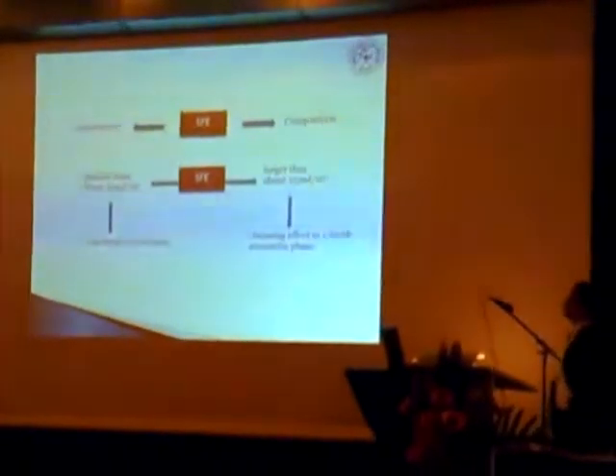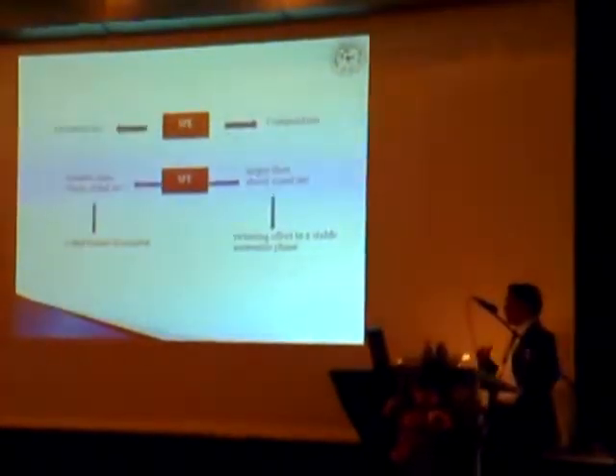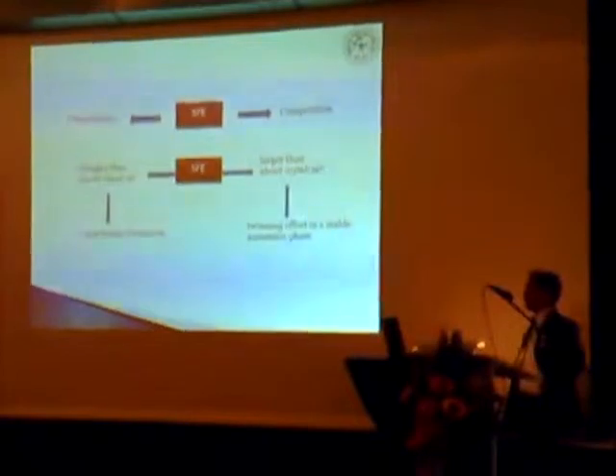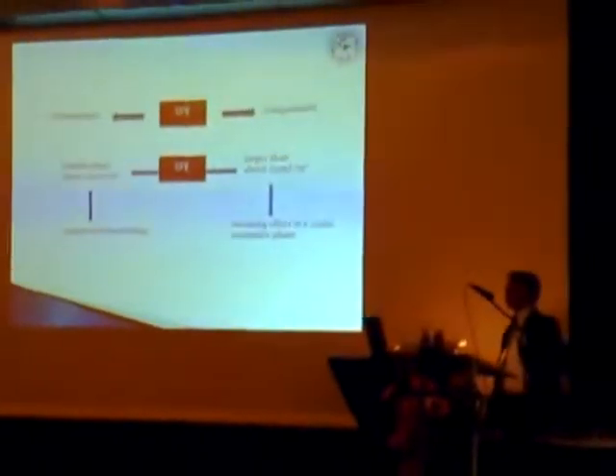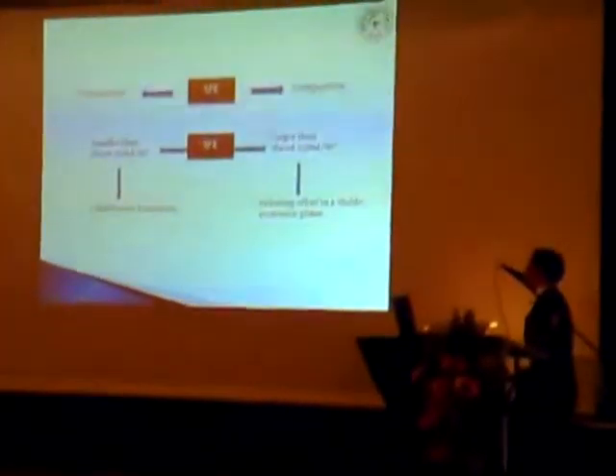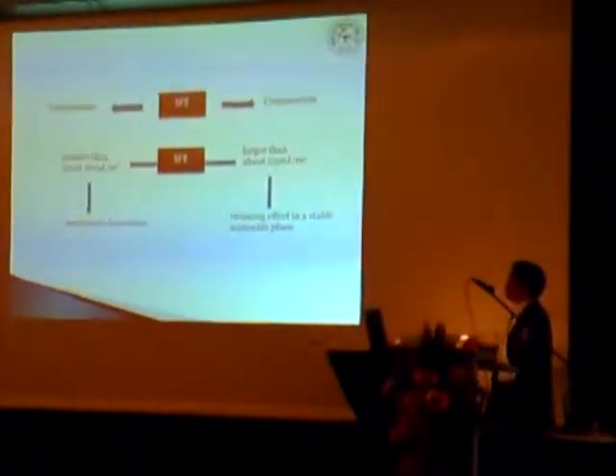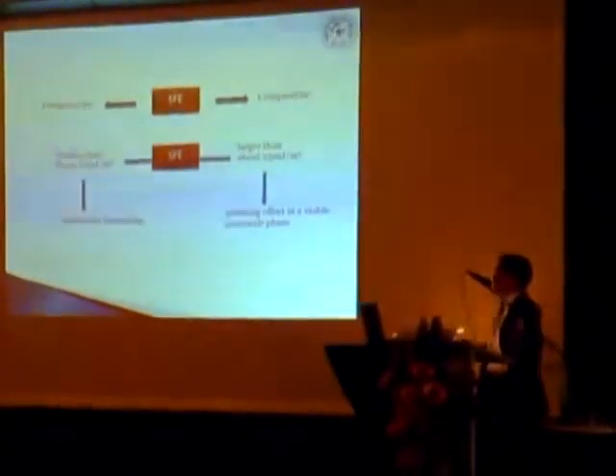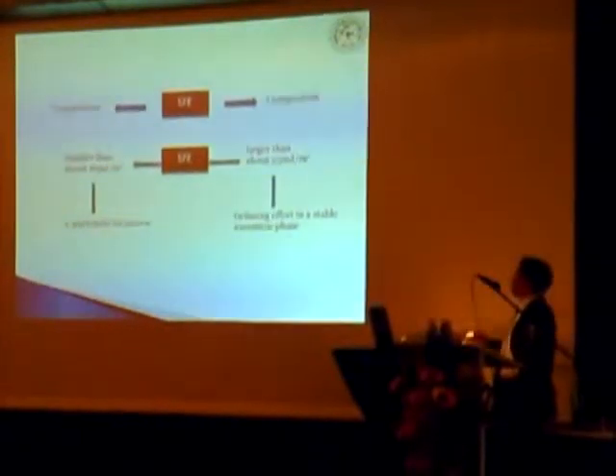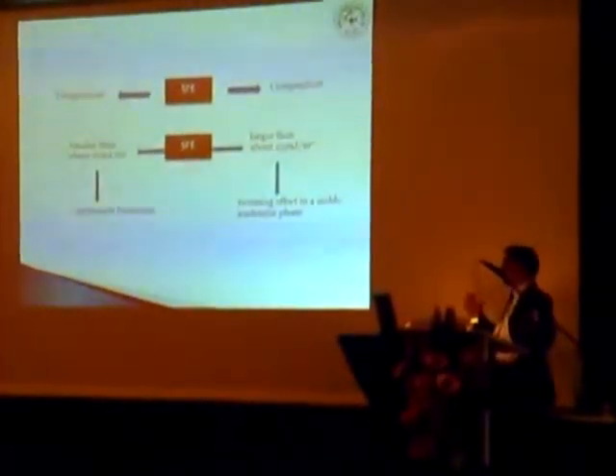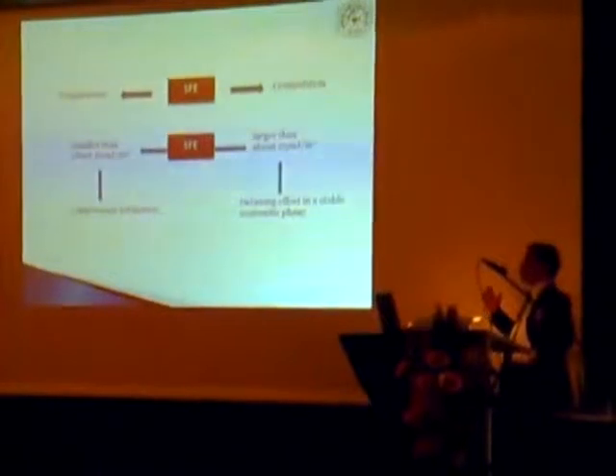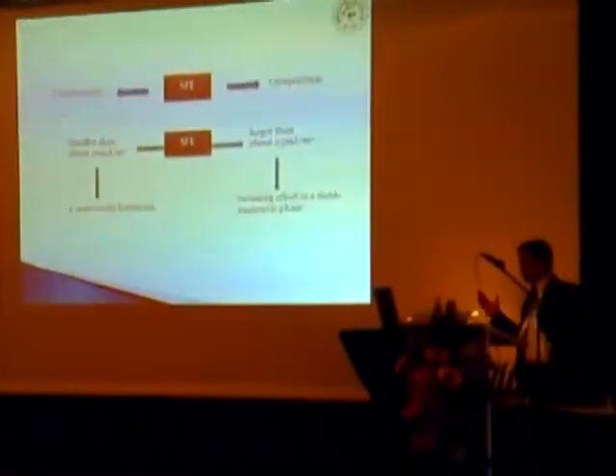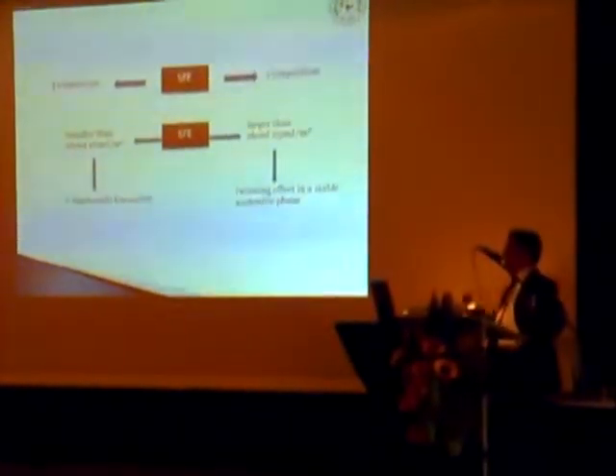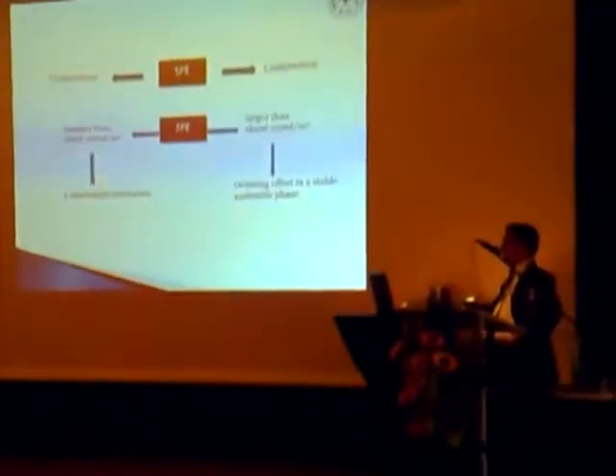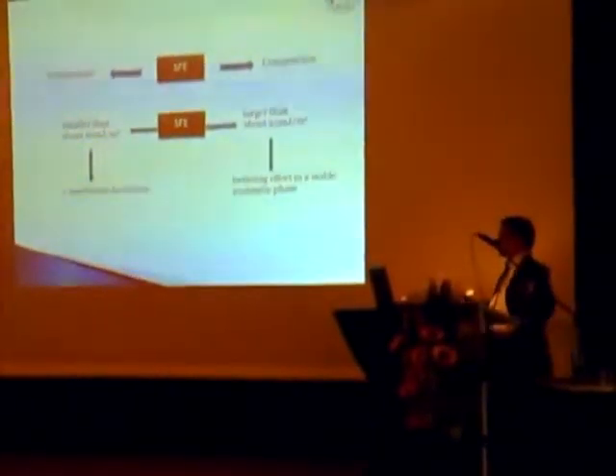And stacking fault energy is proportional to temperature and composition. There is a lot of work on this in twinning-induced plasticity steel because it is thought of as an automotive steel, and that's why people are so involved in that. They say that if it is lower than 16 millijoules, they can form some epsilon martensite. If it is a little larger than that, then there is no effect. Of course, these values, 16 or 25, are based on some kind of ab initio calculations, and we really don't know how valid this is, because in a practical sense, this has no meaning. We only bother about whether...